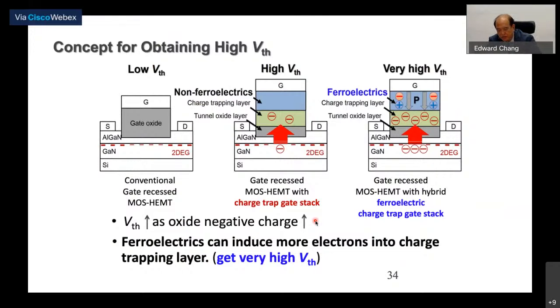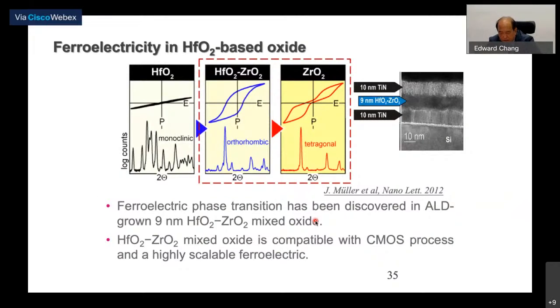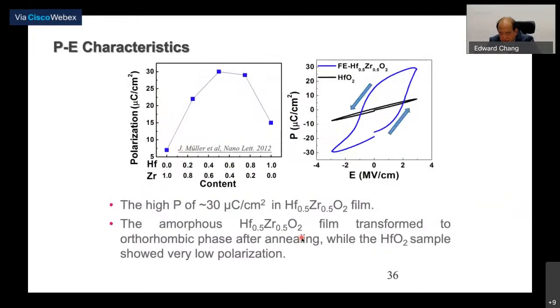This is the charge trapping material and the ferroelectric material we use, hafnium oxide and hafnium zirconium oxide. It is formed by ALD at 9 nanometers. The good part is that this is CMOS compatible, so you just apply the technology to your device. And this must be hafnium zirconium oxide, because neither hafnium oxide nor zirconium oxide alone has the feature we want. This is the PE curve showing the characteristics of this material, and a high polarization of 30 microcoulomb per centimeter squared can be observed in hafnium zirconium oxide.